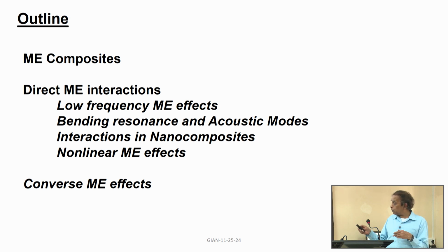So, we will discuss the low frequency magnetoelectric effect, and then what happens is you can apply the magnetic field at a variety of frequencies, there is no limit. So, if I have a bulk composite or a layered structure, I change the frequency of the magnetic field. The frequency may be exactly the same as the frequency of acoustic waves. You should be able to excite standing waves in the composite.